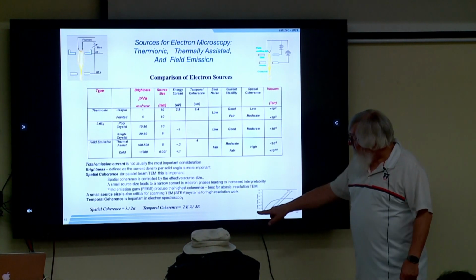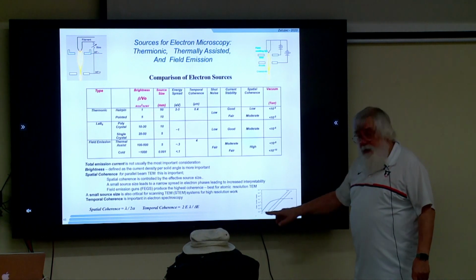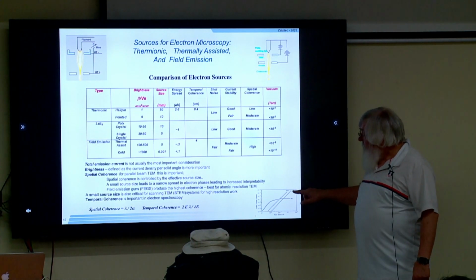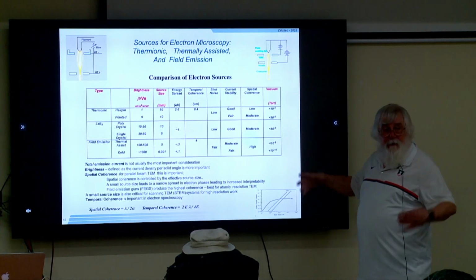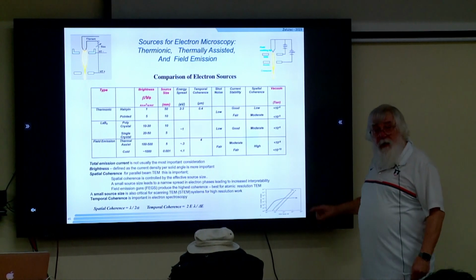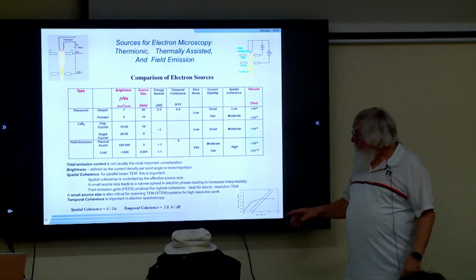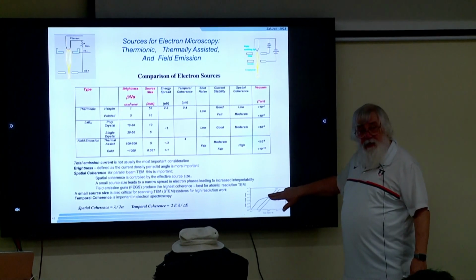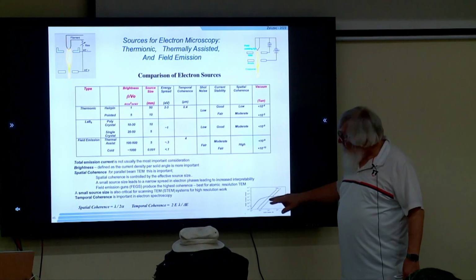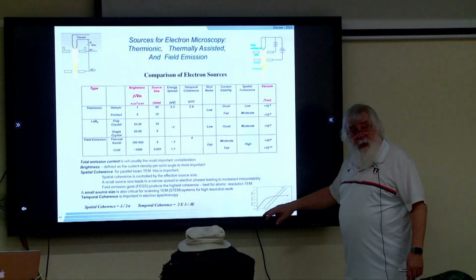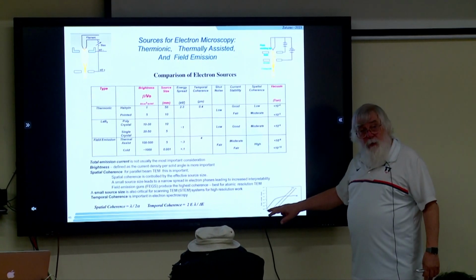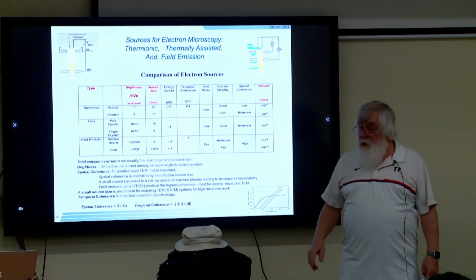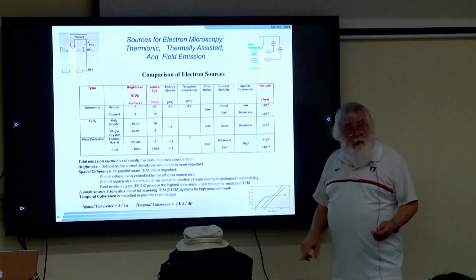So this is a function, this is probe size versus current. The very large probes, the tungsten and the LaB6, have a lot of current and they're very big probes. The field emission guns peter out as the probe size starts to get smaller. For smaller and smaller probes, the amount of current decreases dramatically. So when we want really small probes, we tend to go to a field emission gun. So we have lots of current in small probes.